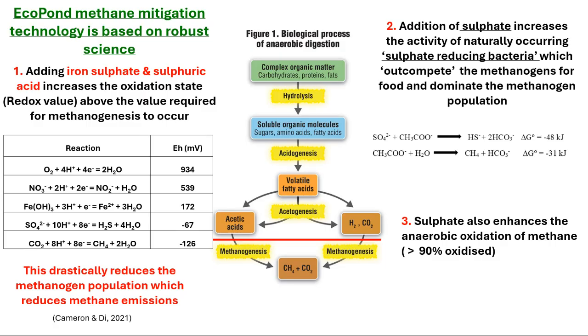So what we've done is treat the effluent pond with two chemical compounds, iron sulfate and sulfuric acid. There are several mechanisms involved that can suppress methane production, but I'll list three here. The first, probably a very important one, is that these compounds raise the redox potential of the effluent. If you do not add these, the pond is very anaerobic. It usually goes down to -200, -300 mV, we measured. Under these conditions, the methane-producing microbes, the methanogens, love it. They are very active producing methane. Once we raise the redox potential to about +200 or so, they are dead, because under aerobic conditions they cannot survive. So they are not able to produce methane under those conditions. That's the first mechanism.